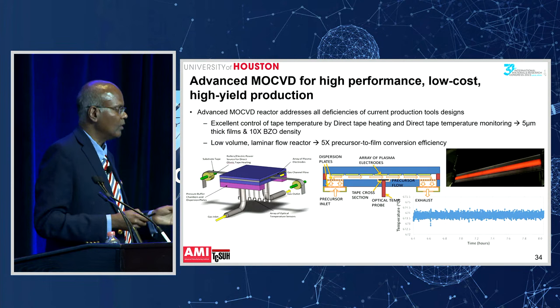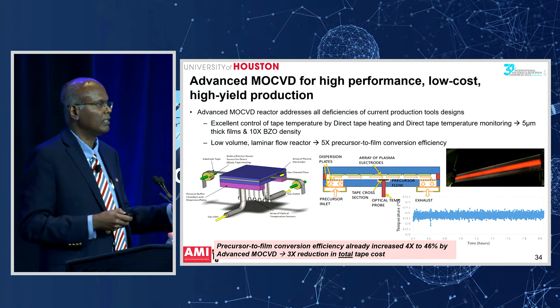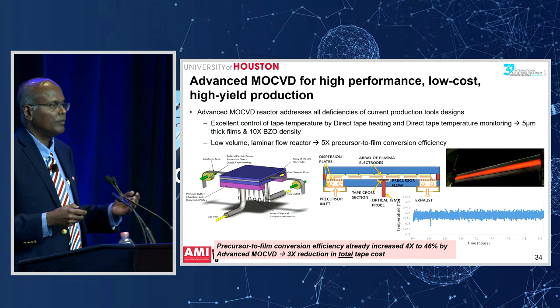control, and we're also converting the precursors a lot more efficiently, about 4 to 5 times more efficiently, to the superconducting film. That also improves the cost. So with this method, our goal now is to make thick films to get higher currents. So that's what I'm showing here.